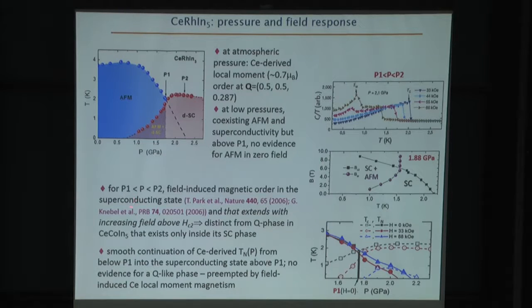On the other hand, Tuson Park and Georg Knebel have shown that if you tune cerium rhodium indium-5 to pressures between what we call P1 and P2, where there is only superconductivity in zero field, but now you add a field to cerium rhodium indium-5, you see first a superconducting transition in heat capacity, followed by a rather large anomaly in this case in the specific heat. This signals field-induced magnetic order. Here we just show data at a representative pressure of somewhere about here, but you see very similar behavior at other pressures between P1 and P2.